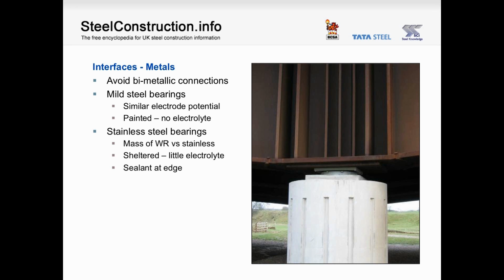For stainless steel bearings, there is an issue in that there is a significant difference between the electrical behaviour of weathering steel and stainless steel. In addition, the stainless steel bearings are exposed to the elements, so there is contact with the electrolyte. However, the surface area of the weathering steel is so vast in comparison to the stainless steel bearing that the effect is very small. In addition, the girders and the bearings are generally sheltered, so the time that the electrolyte is present again is very small.